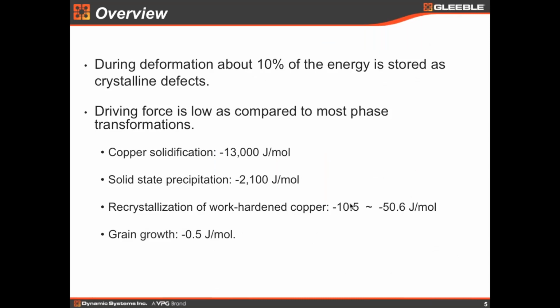It's important to remark that of all the energy spent to deform a metal, only about 10% is stored in the metal as dislocations and other defects. And this is actually the driving force for the recrystallization to occur. This driving force is very low compared to other phase transformations. For example, copper solidification has 13,000 joule per mole, solid state precipitation 2,100 joule per mole, and recrystallization of work hardened copper could be from 10 to 50 joule per mole. So we see there is an order of magnitude difference, and grain growth is even smaller. We'll cover these numbers later in this presentation.